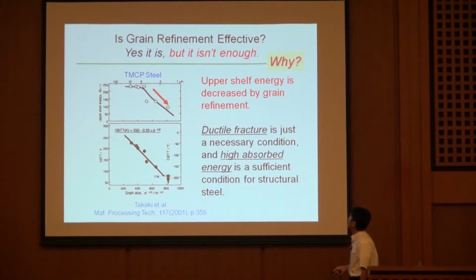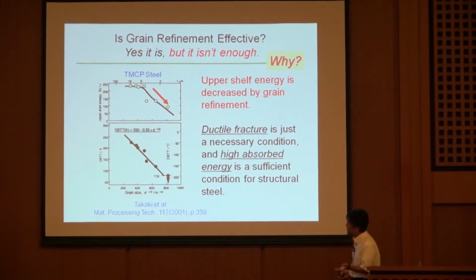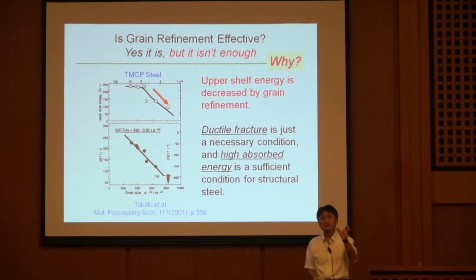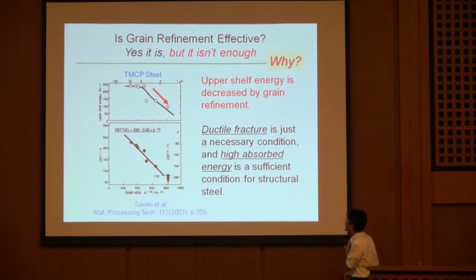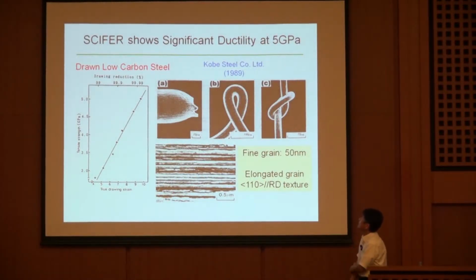So what I want to say is, upper shelf energy is decreased by grain refinement. See? So then the ductile fracture isn't a sufficient condition. I need absorbed energy higher than 100 joule. So I should say a high absorbed energy is a necessary condition for structural steels. So then we discussed again and again, and there was one good hint.